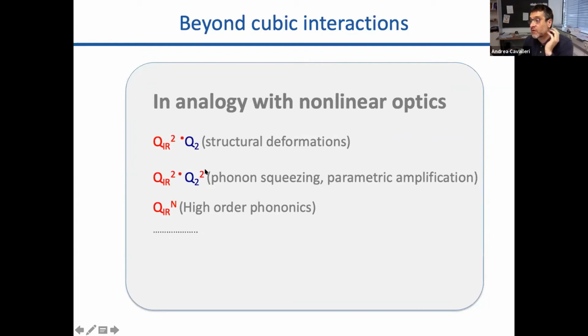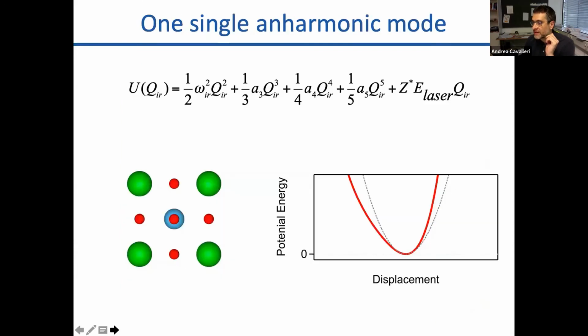You can look at effects of 4th order, such as Q square, where I could achieve quantum squeezing of phonons, for example, reducing the noise on a specific phonon mode at the expense of the coupling to another one. Parametric amplification, so I can almost make a phonon laser by amplifying these phonons by many orders of magnitude. And high order responses. I'll just very briefly make an example of where this Q to the N turns out to be interesting. So very briefly, you can take a material and just pump 1 single mode. This is a material which has a very strong, in this case it's a particular ferroelectric, but it's not very important, which has a very strong anharmonicity in the phonon coordinate.